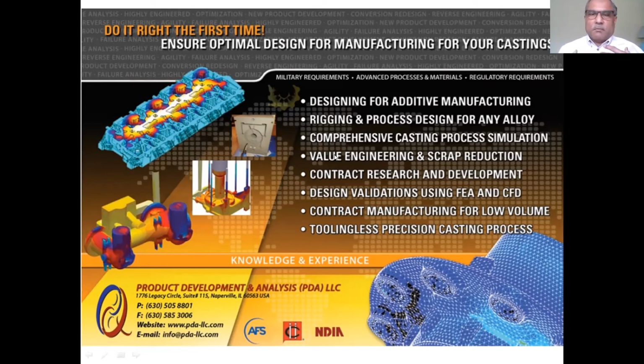What we are referring to for metal casting is strictly a binder jet process where we make the mold, a sand mold, out of silica sand or ceramic sand, and make the core, which goes into the mold to make your interior features, again made with binder jetting, layer by layer, and you make the cavity where you pour the metal. The main distinction is in our approach of additive, we use the same alloy, which has the same cooling rate as conventional sand casting or investment casting, as opposed to metal additive, where they have a tremendously high cooling rate. So the properties you get are nowhere close to what the alloy was designed for.